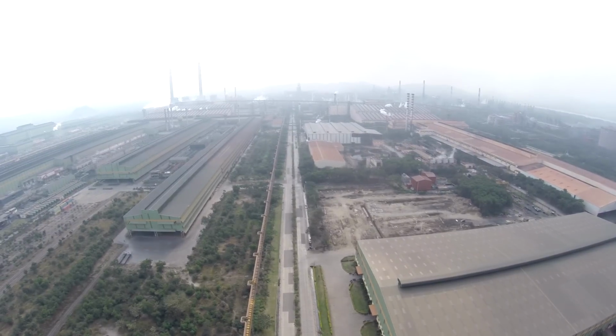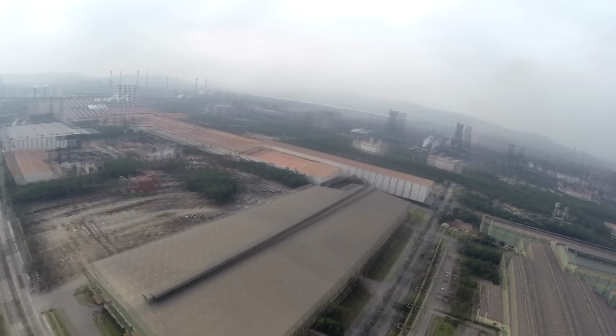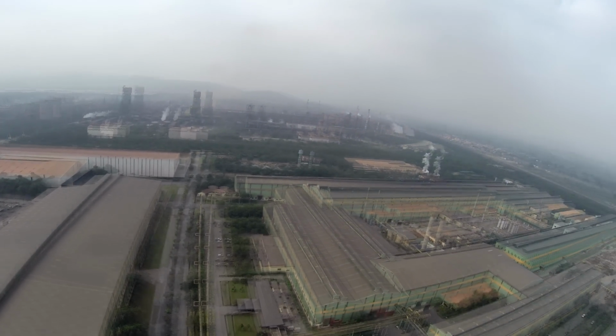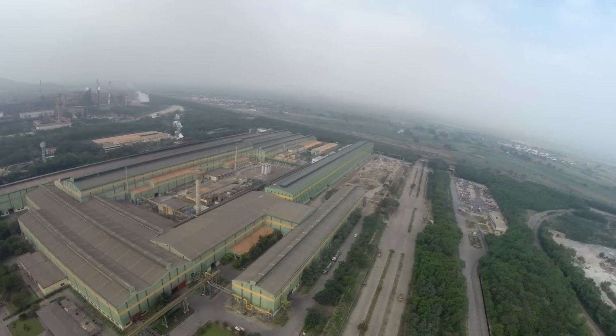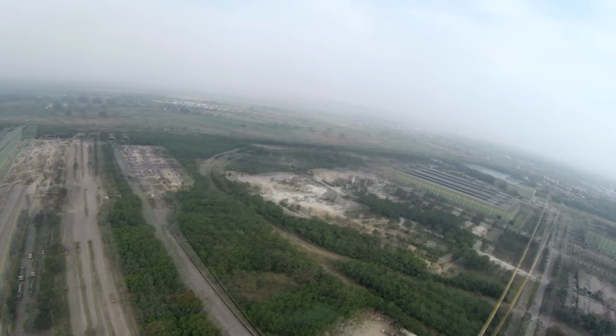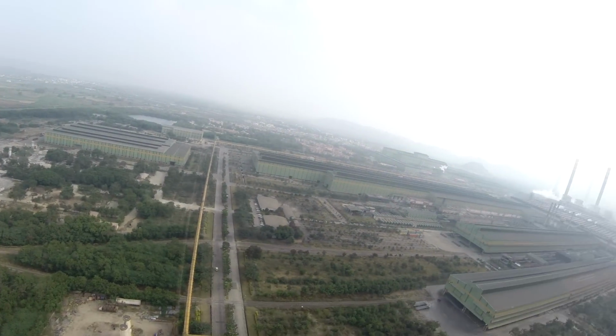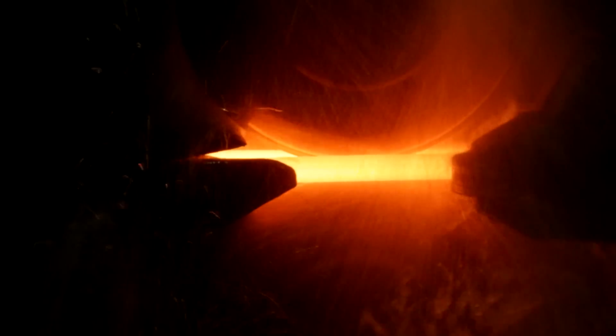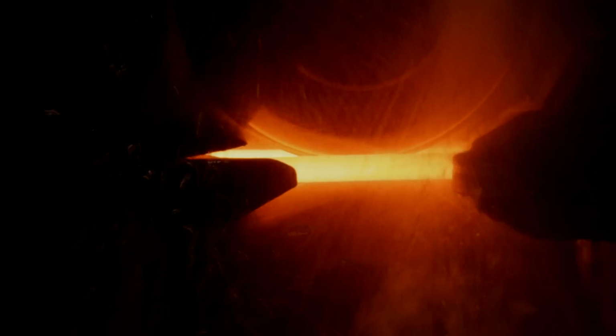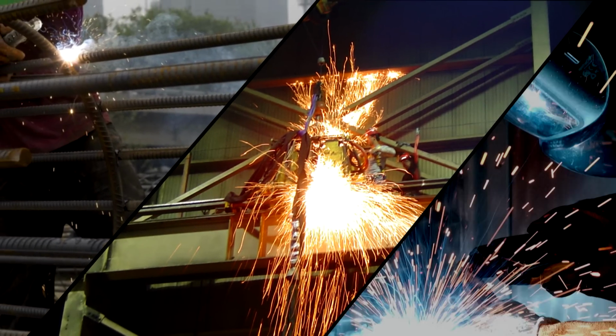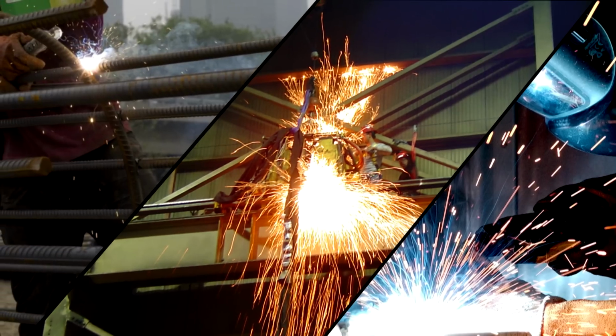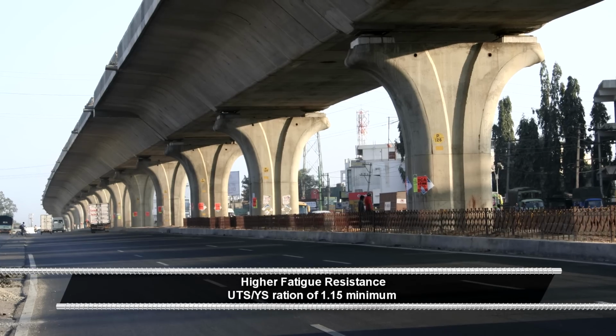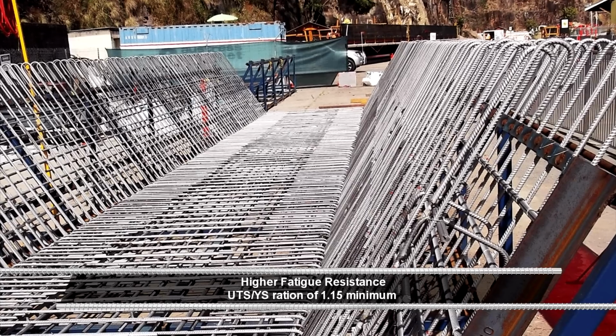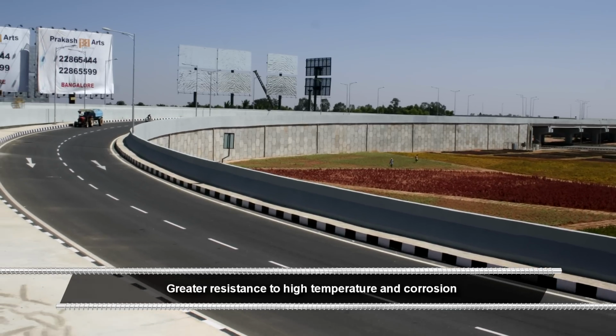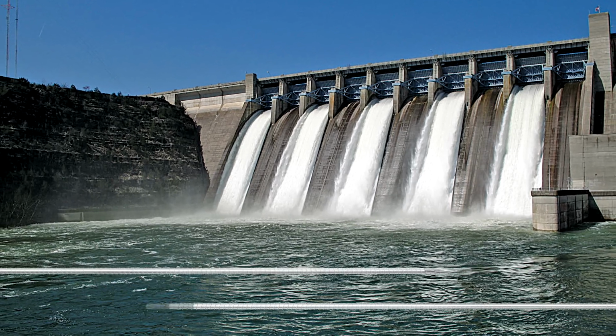JSW's state-of-the-art rolling mill ensures excellent yield strength, exceeding the values mentioned in the standard IS 1786 and ASTM Grade 40, Grade 60. The manufactured bars have excellent weldability, can be easily butt welded, lap welded, and arc welded manually without any preheating. They have higher fatigue resistance and bendability, greater resistance to higher temperatures and corrosion.